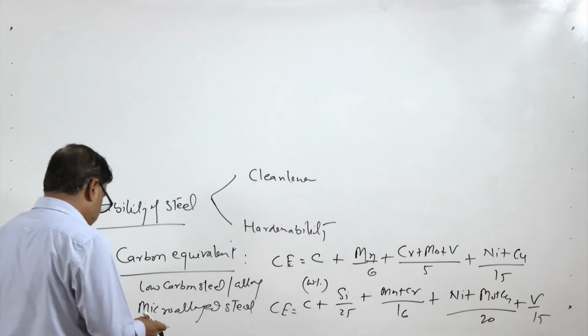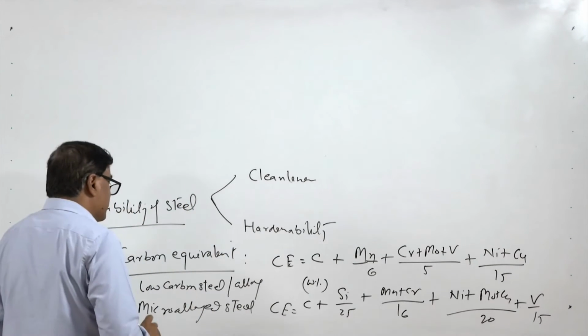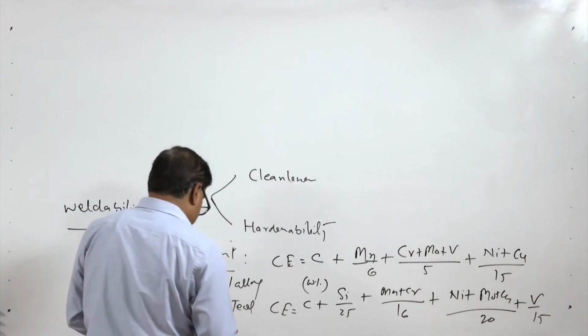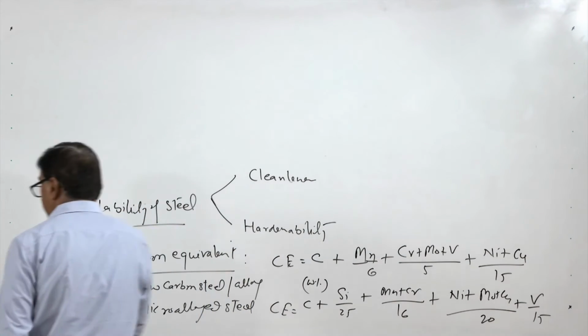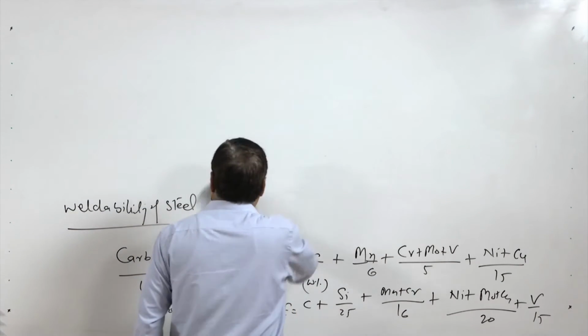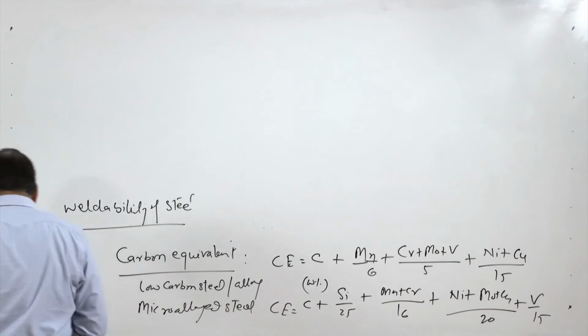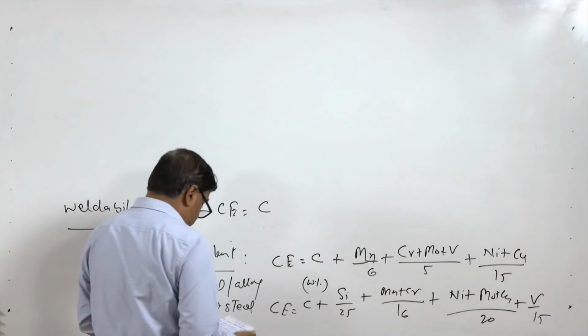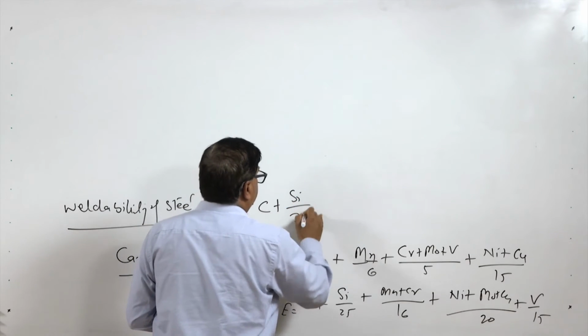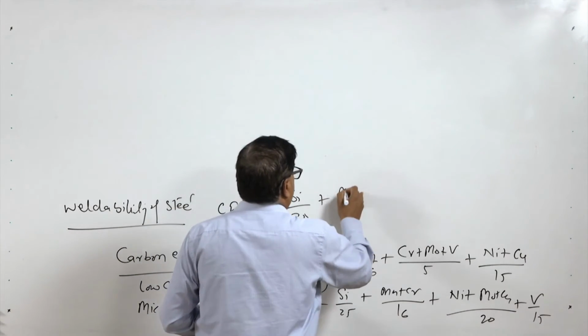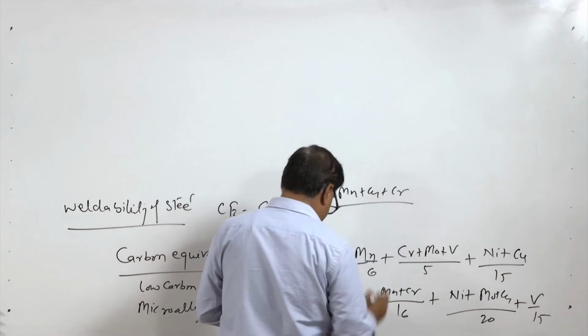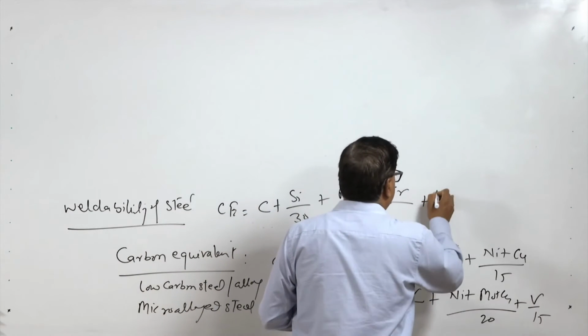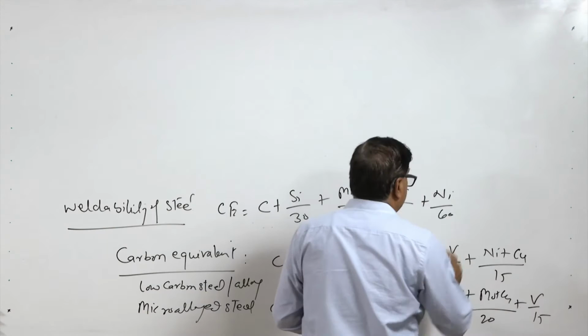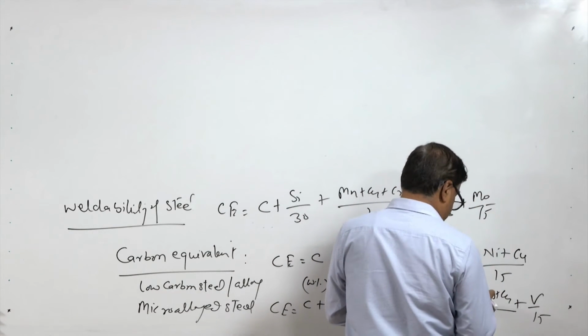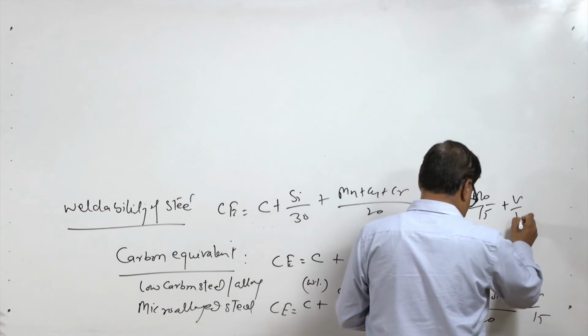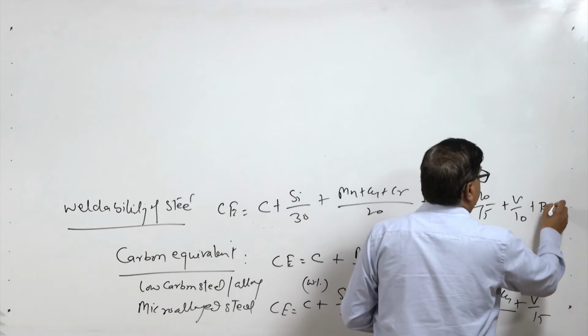So, this is another equation, and likewise there are other equations also which are used. For example, there is another equation for calculating the carbon equivalent that goes like this, where CE is equal to C plus silicon divided by 30 plus manganese, copper, chromium divided by 20, nickel divided by 60, molybdenum divided by 15 and vanadium divided by 10 plus boron multiplied by 5.